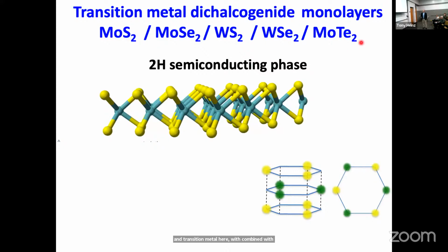And this is what we call a monolayer. It's a stoichiometric monolayer. It actually looks a lot more complicated than graphene, you might think. But if you take a top-down view of the structure, it has this kind of honeycomb lattice, just like graphene. The difference is that instead of having the same atoms on the A and B side, you have metal atoms on one side and the chalcogens on the other, but the chalcogens are displaced a little bit vertically. So actually, from the point of view of symmetry, it's very similar to graphene with the broken AB sublattice, and is actually identical in terms of two-dimensional symmetry with hexagonal boron nitride.